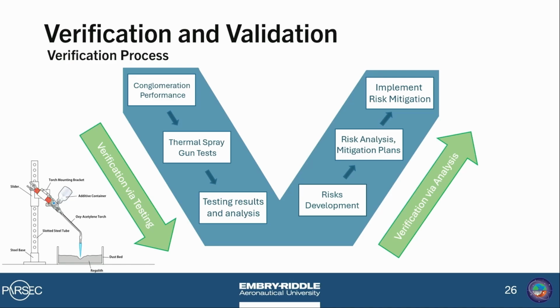We utilized 2 types of processes for this. The first was a test which we conducted with alumina and nickel alloys onto a test bed of lunar regolith simulant. During our testing, it was imperative that we confirm the applicability of our product for NASA's specific needs and the intended environment. Due to constraints like cost and time, we were unable to fully replicate any real conditions. However, we were successful in our conglomeration with the nickel alloy, suggesting the potential utility of our design for future